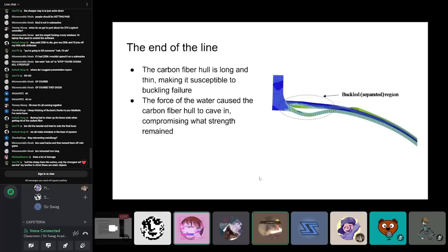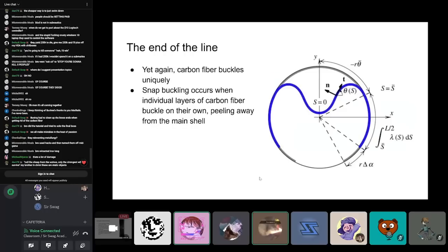So, in the end, what happened? The carbon fiber was long and thin, meaning it probably buckled. It means the carbon fiber caved in, and it just put a hole in it, and all 5,000 pounds of pressure per square inch came in and flattened everybody. But, because we can never have nice things, carbon fiber buckles uniquely. We got something called snap buckling. That means individual layers of the carbon fiber peeled away from each other.